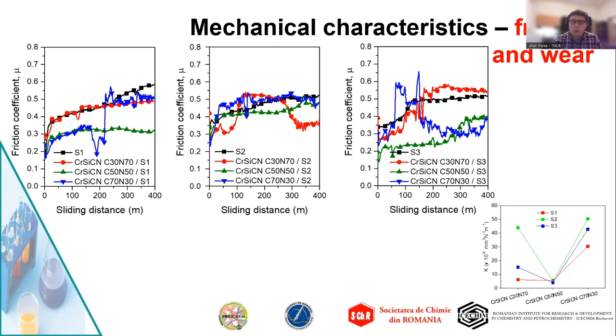And the lowest wear rate, as you can see here below on the right, was obtained also for the coating in the middle in this representation.